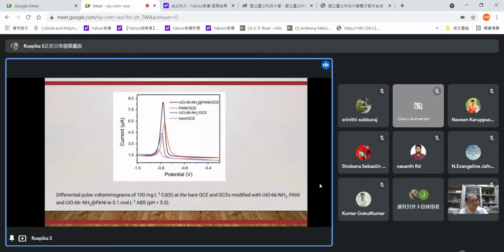And the electrochemical response was investigated using the DPV, and a small oxidation peak was observed at bare GC. When the UiO66-NH2 was coated on the electrode surface, the oxidation peak current increased significantly, and the oxidation peak current was larger than those of the two electrodes before. This is because the polyaniline can increase the conduction pathway and promote the electron transfer between the solution and the electrode surface. The UiO66-NH2@PANI modified GCE shows well-defined peaks and almost tenfold current increase in response to the cadmium ion, which is credited to the synergetic effect of the composite with the polyaniline.